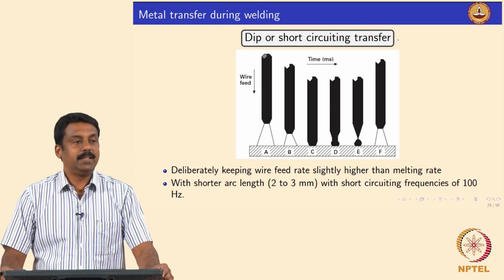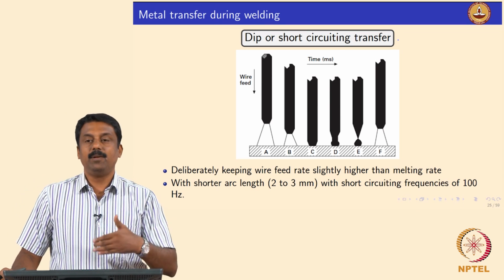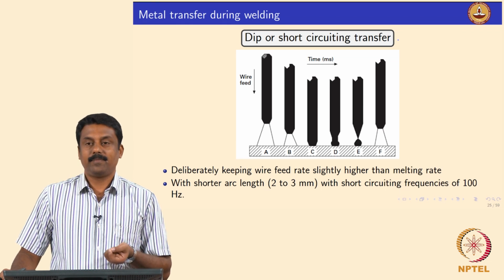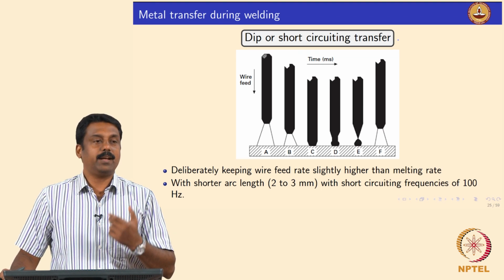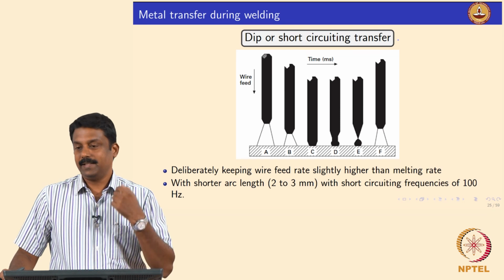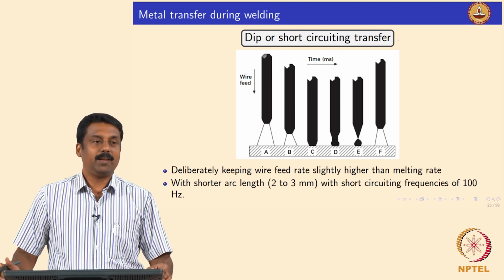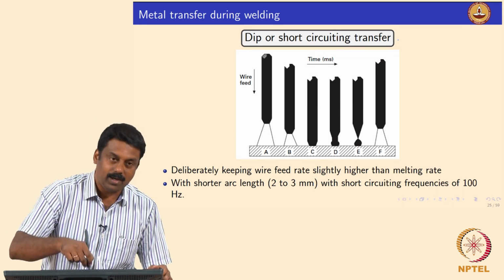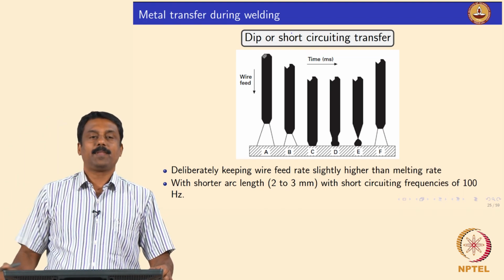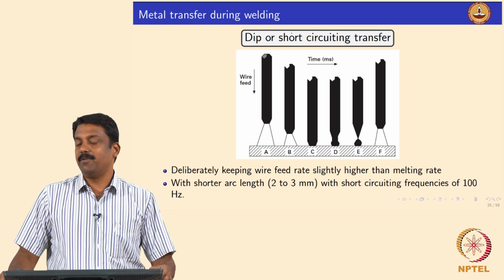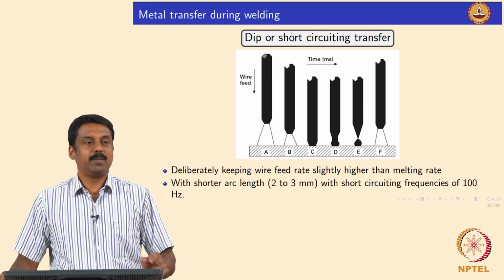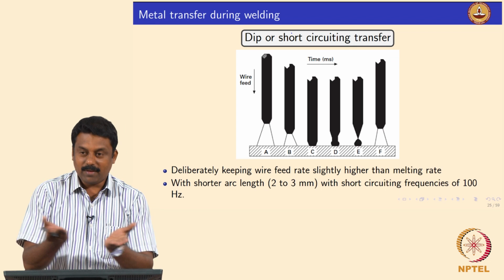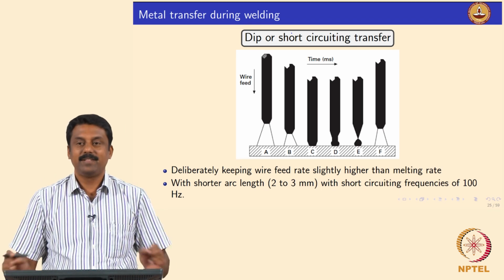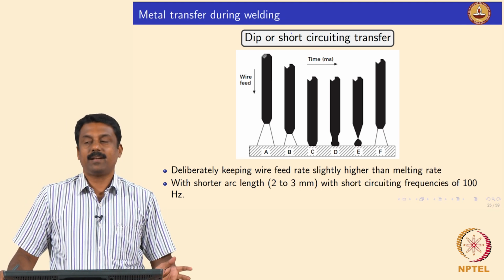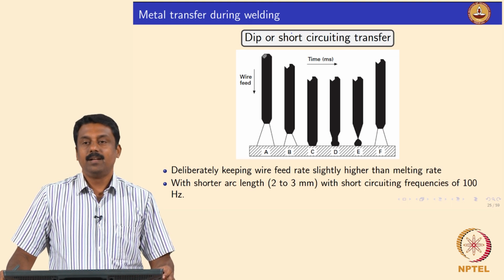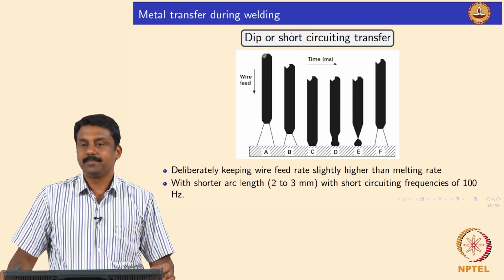So, other mode of transfer. So far we looked at free flight transfers, okay, and you can also achieve the stable transfer by dip. What do you mean by dip? So, you can also touch the droplet once it formed onto the pool, and when you pull it back, so you also change the force balances. You can overcome the surface tension because the liquid pool surface tension would make sure that the droplet is detached, right. So, that kind of transfer is known as dip transfer or short circuiting transfer.